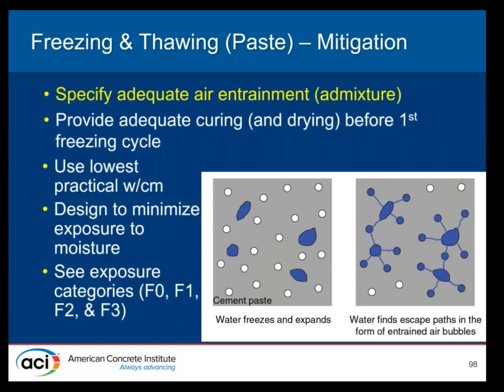If we have air entrained concrete, we specify an adequate amount of air depending upon exposure conditions and the size of the aggregate. And the air voids provide space for the expanding water to move into, and that minimizes or prevents concrete cracking. This is the simplest explanation we can do for this one. So if we have adequate curing and drying before the first freezing cycle, we have air voids inside the concrete. Water can move into those air voids and finds an escape path there that provides basically a relief valve, or spots for the water to freeze into. So then when it's exposed to freezing conditions, it doesn't crack.